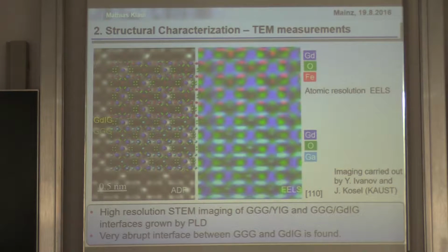And it's quite amazing because the unit cell of YIG has many, many atoms inside. It's really complex. But it just shows you, if you have a compound that nature likes, it's also easy to make. Most often, the problem is that the compound we are interested in tends to be the one that nature doesn't like. For instance, in oxides, nature likes to have a certain oxide, like in chromium oxide. There's a ferromagnetic oxide, CrO2, but nature prefers Cr2O3. So you have to really trick nature into getting the right material to work. But with YIG, YIG loves to grow the way it grows.